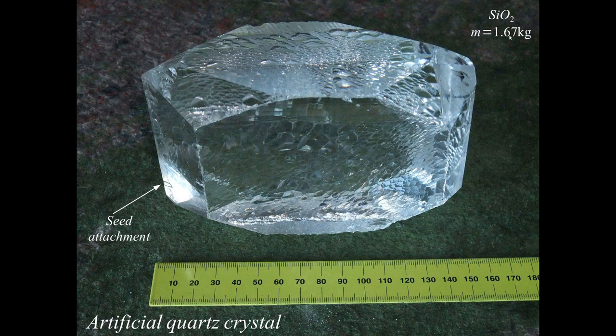This quartz crystal weighs almost 2 kilograms, and the cost of this is around $30. So it's not a particularly expensive material, because temperatures are not that large as when we are processing silicon or other semiconductors. Here we have hydrothermal growth at low temperature, but still very high pressure. The surface is not particularly smooth, but the crystal inside is almost perfect. And this crystal is then sliced into thin plates to make our resonators.